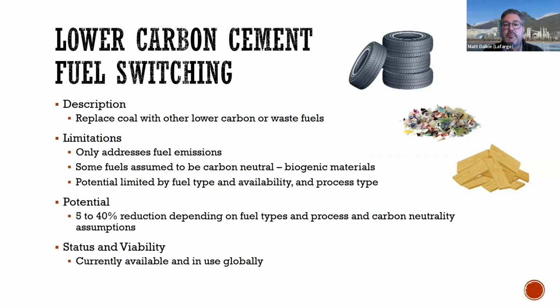Some fuels are assumed to be carbon neutral, and these are biogenic materials or biogenic fuels, as well as a biogenic portion of some of the other fuels, like tires, for example. They do have a certain level of biogenic content in there, so that's taken into account as well. In terms of how much fuel can be used, it is limited by the fuel type, what the fuel source is, and the process type, but we can reduce somewhere between 5 to 40% of our total emissions for cement production by switching to these other alternative fuels. And this has been in use and available worldwide for a number of years now.